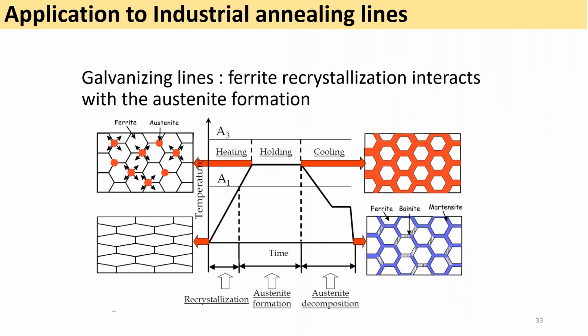I'd like to show you this same type of study, but for an industrial case in a galvanizing line. This type of study is very important. We need to have a reheating of a sample, which is initially cold rolled, so as to recrystallize the sample. This recrystallization will occur in the two-phase domain, so we have to be sure that the austenite formation and the recrystallization do not interact with each other, because it would lead to heterogeneous microstructure, which is non-desirable.